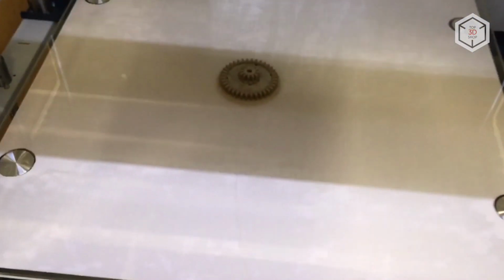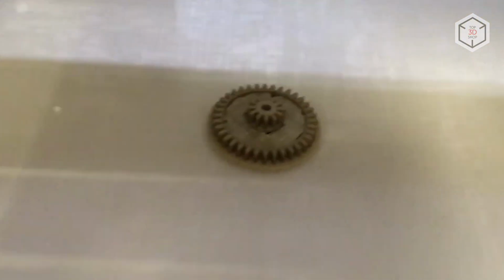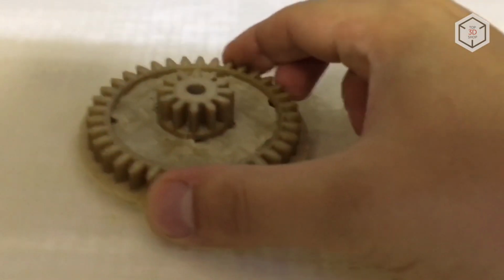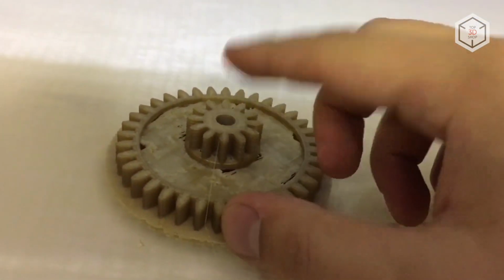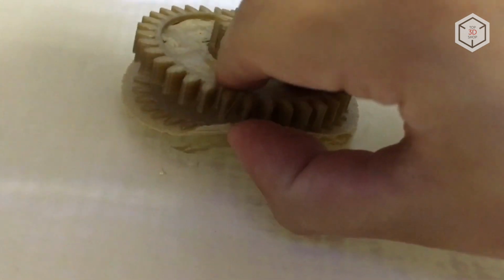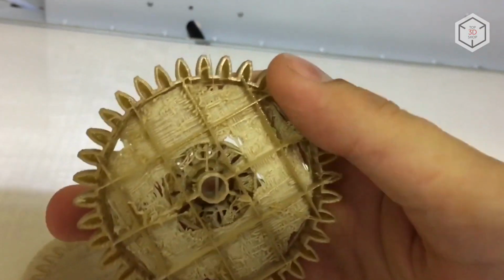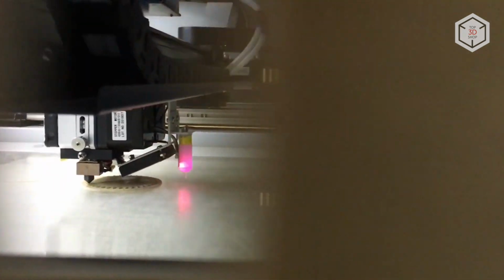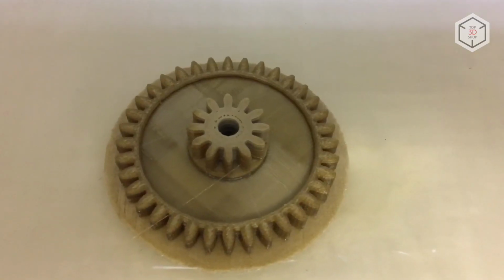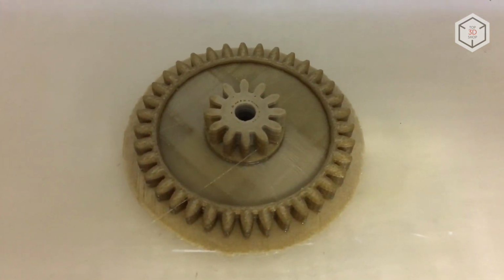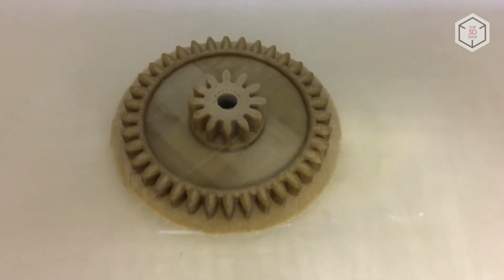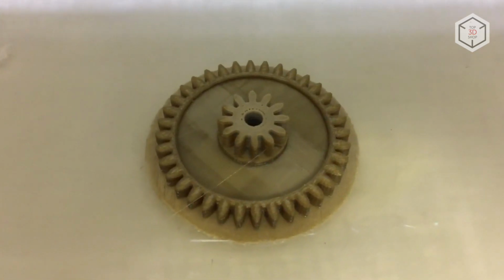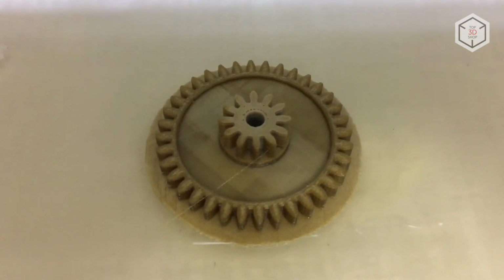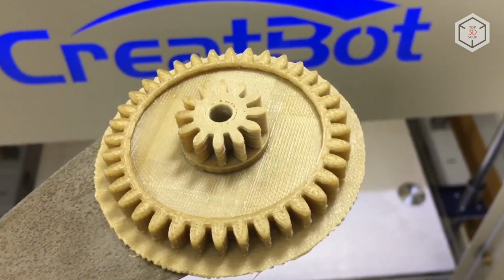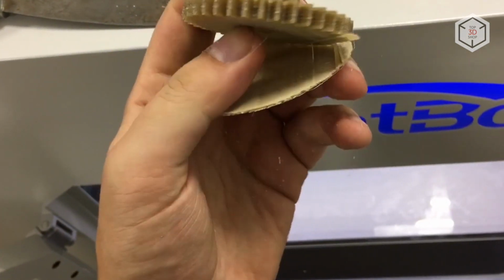The print job is complete, and already by the appearance of the finished part, we can say that the result is hardly satisfactory. Looks like the settings need adjustment. The model is quite difficult to remove from the bed. It also seems that the infill percentage was too low. Reprinting with updated settings is complete. The result is clearly different from our previous attempt. Let's wait until the temperature of the platform drops to overcome the strong adhesion of the glue. Let's tear off the support base, slightly cleaning up the part which was printed with 100% infill.